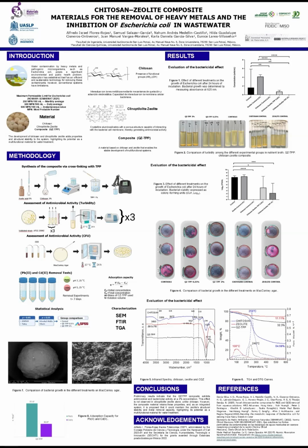After stirring was complete, the chitosan zeolite mixture was added dropwise to a cross-linking solution of sodium tripolyphosphate. Subsequently, the composite was washed with distilled water until a neutral pH was reached and dried at 35 degrees Celsius for 72 hours. The antimicrobial activity of the composites was evaluated using Escherichia coli strain ATCC 25922. Standardized bacterial suspensions were prepared and adjusted to a turbidity equivalent to 0.5 on the McFarland scale.